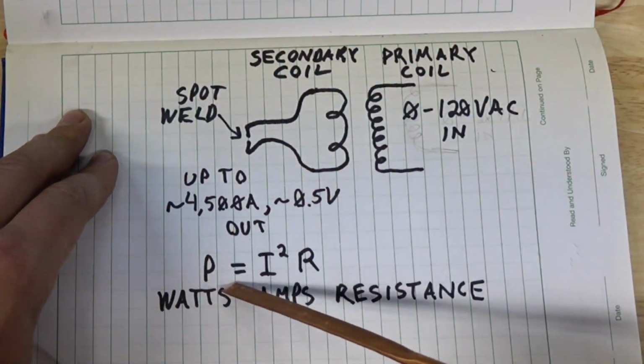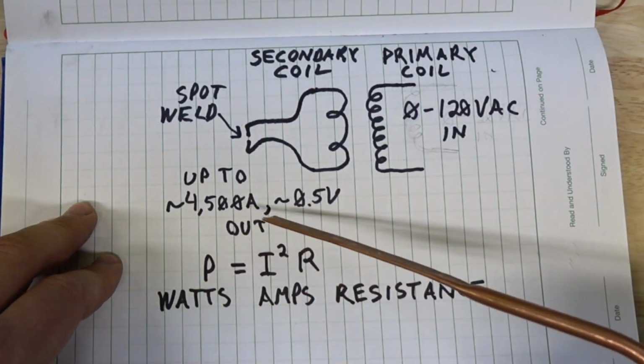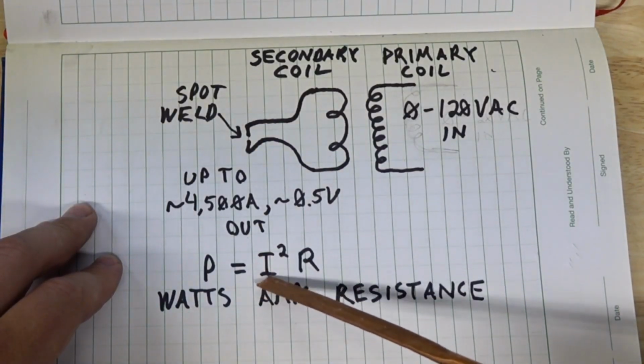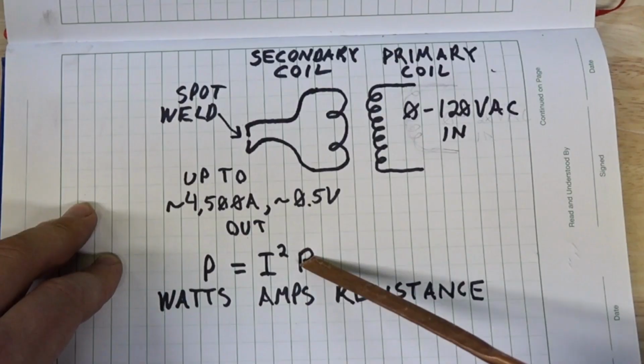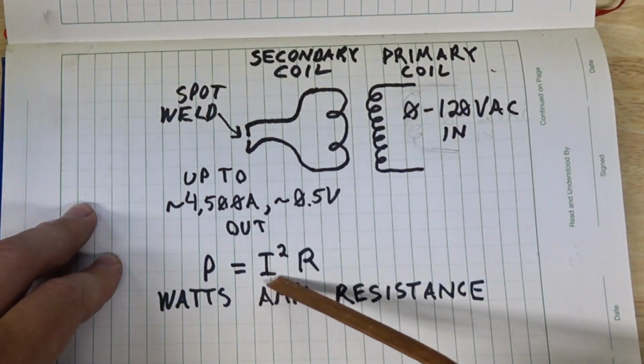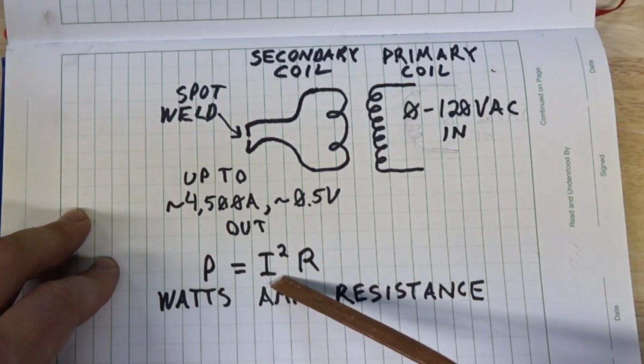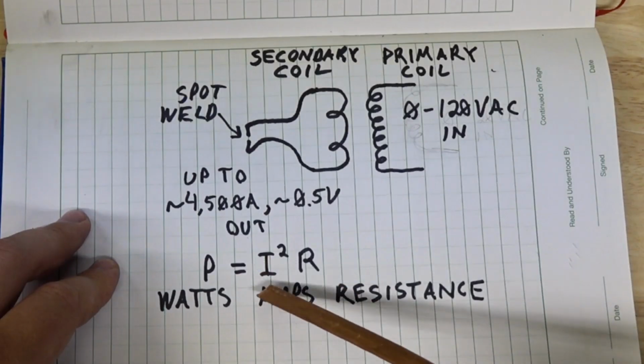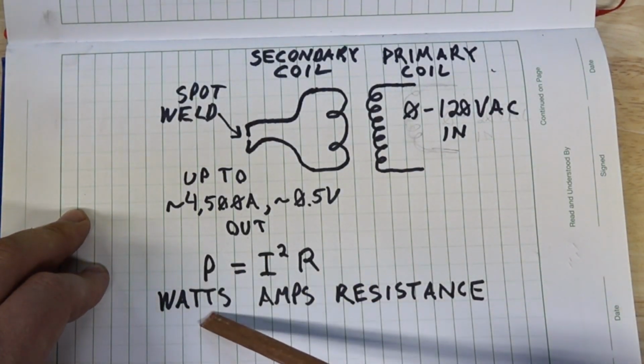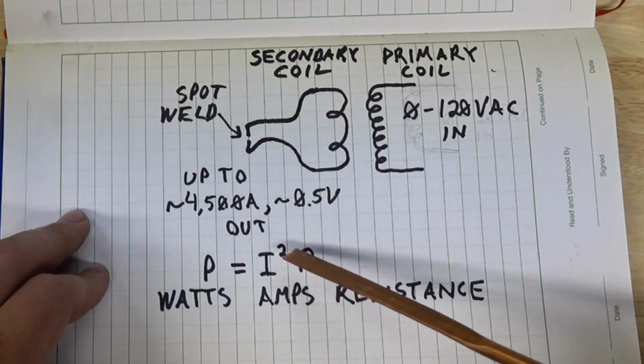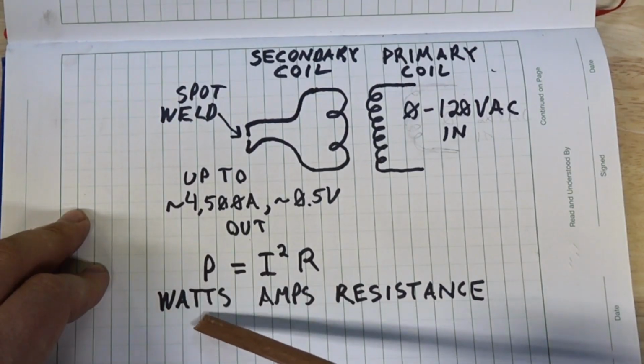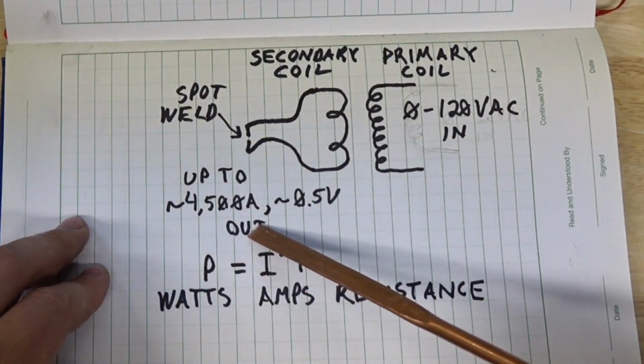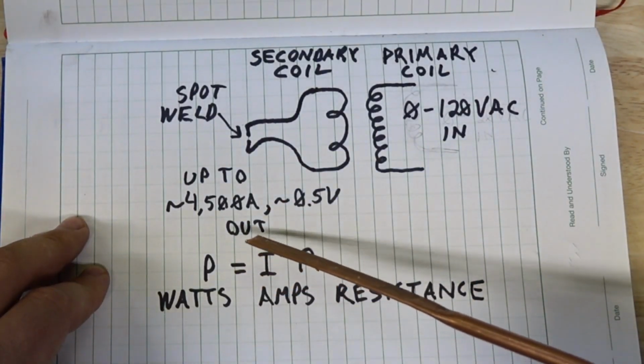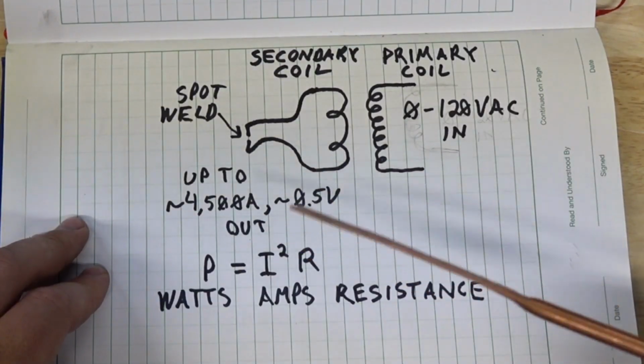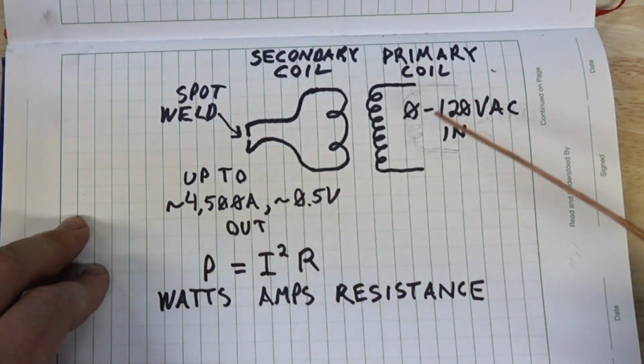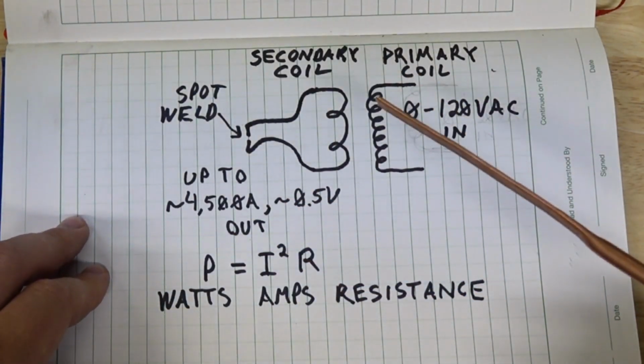but you are taking advantage of resistive heating with this system. The resistive heating formula gives you, power in watts is equal to amperage squared times the resistance of the material through which the current is being passed. And so if you can up your current that you're passing through the material, your power goes up with the square of the current. And so you can dump a bunch of wattage through a material if you have a very high current passing through it, and it leads to immense heating, and eventually the material melts, and so you get your weld. And this is just a really easy way to weld a material.